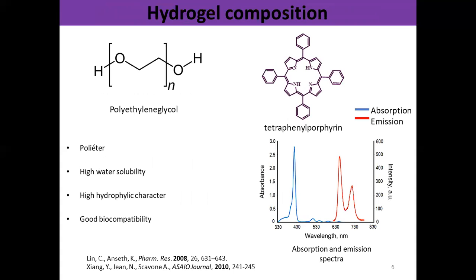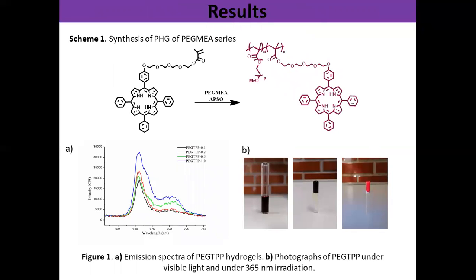The composition of the synthesized hydrogel is polyethylene glycol, which is a polyether with high water solubility, high hydrophilic character, and good biocompatibility. In addition, a monomer derived from tetraphenylporphyrin, a macrocycle characterized by a well-known absorption and emission spectrum. In this work, we present the results toward the synthesis of a new series of polymer hydrogels obtained by frontal polymerization using a porphyrin derivative monomer as fluorescent moiety in a polyethylene glycol methyl ether acrylate matrix.